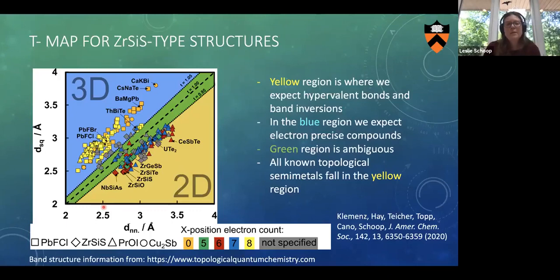But the thing we notice immediately is the yellow and the orange ones are the charge balanced, boring eight electron count things. And they're all here in this blue area. So there's no necessity for a hypervalent bond because these are already happy charge balanced materials. And then everything where the electron count is a little bit off is here in this area. And even more interesting, all the known topological semi-metals in this class of materials fall in this area. And then even unspecified materials like uranium ditelluride fall in this area.